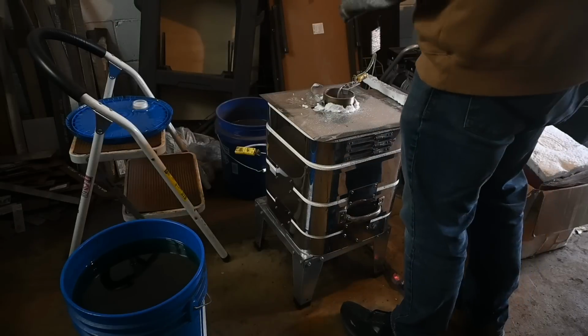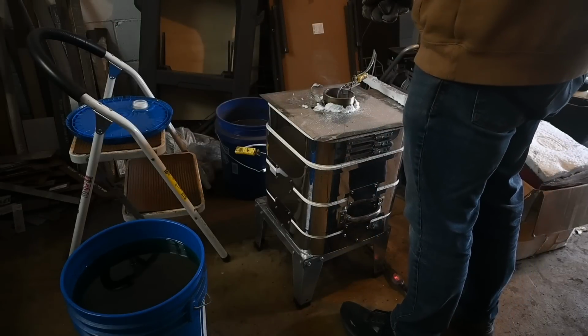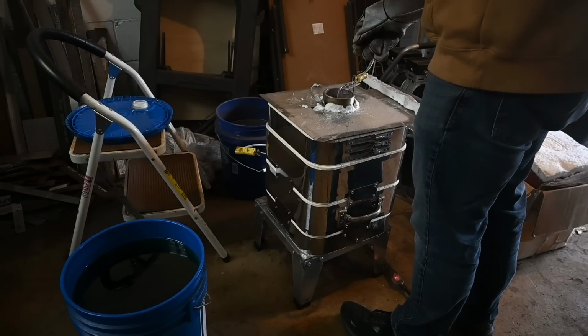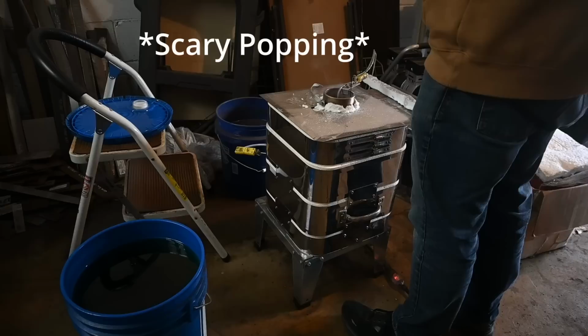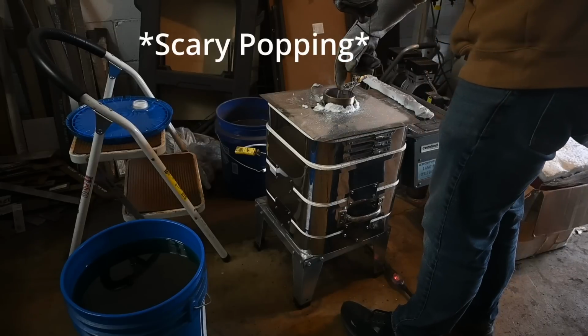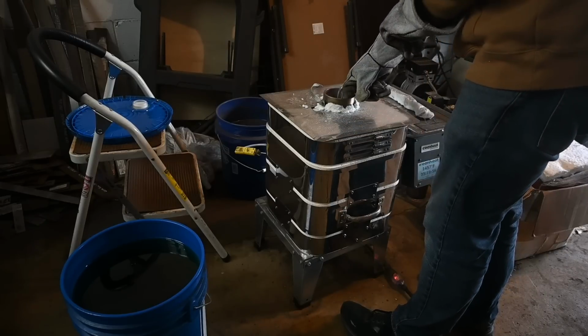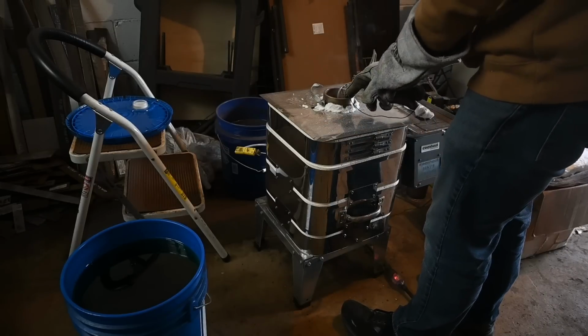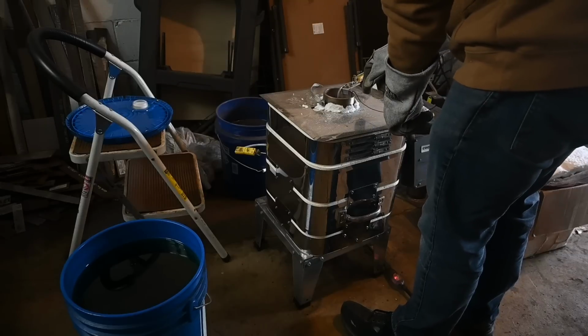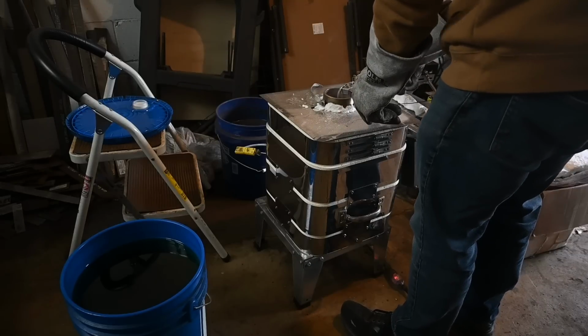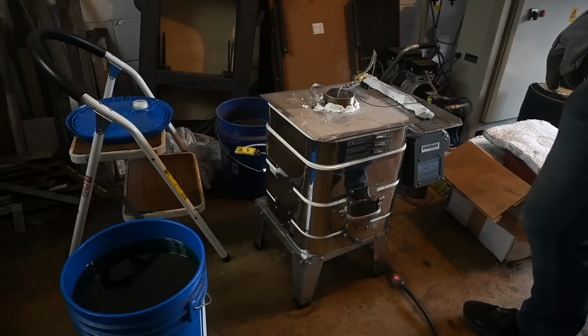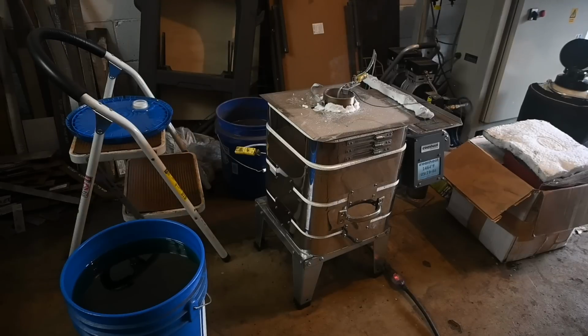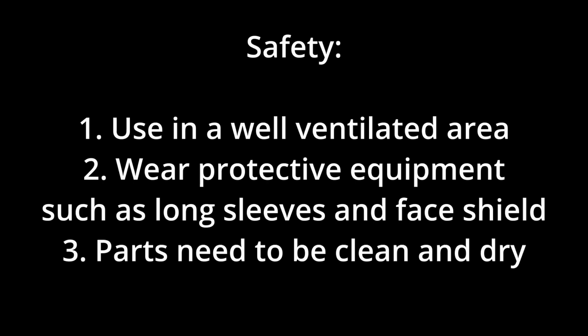If you've ever heard about heat treating in salt pots, you've probably heard about how dangerous they can be. So if you drop significant amounts of water into a salt bath, it can explode. And you would be in a lot of danger if that happened. You know, it's molten hot salt up to 1500, 1600 degrees Fahrenheit. And that'll make a big mess, and you want to avoid all those things.